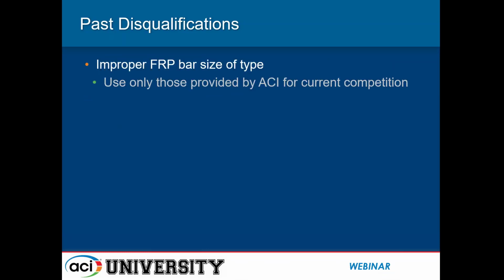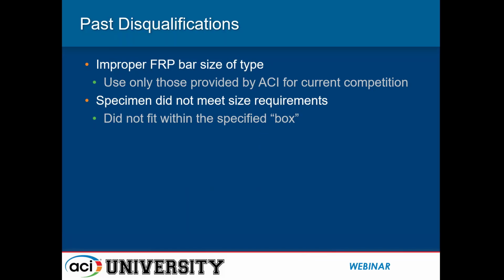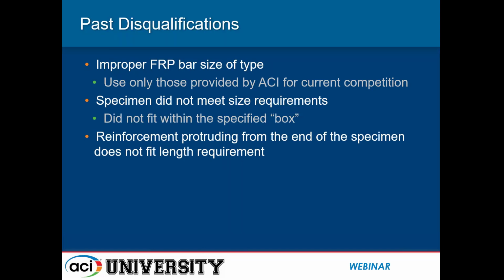Now we'll talk a little bit about past disqualifications, and I've mentioned these as we went along the presentation. First of all, teams have been disqualified for improper FRP bar size or type. Again, please use only the bars provided by ACI for the current competition. Even if your member does not fail exposing your bars, we will dismantle your member and we will verify the bars. The specimen did not meet the size requirement. It did not fit within the specified box or it was too long to fit in the box. Even if the specimen fits within the box itself, if reinforcement protrudes from the end of the specimen, then that does not meet the length requirement.